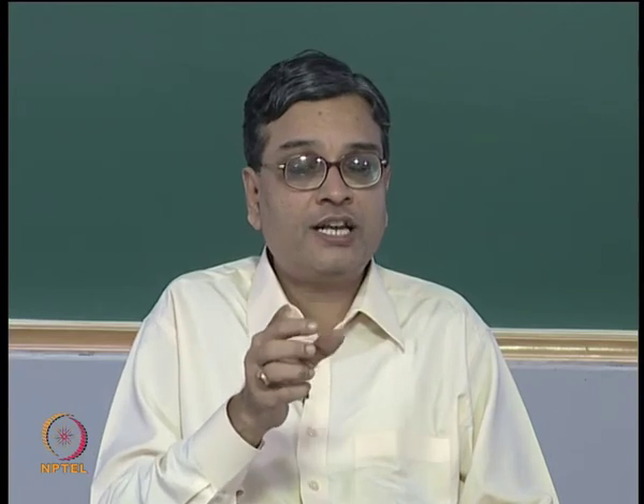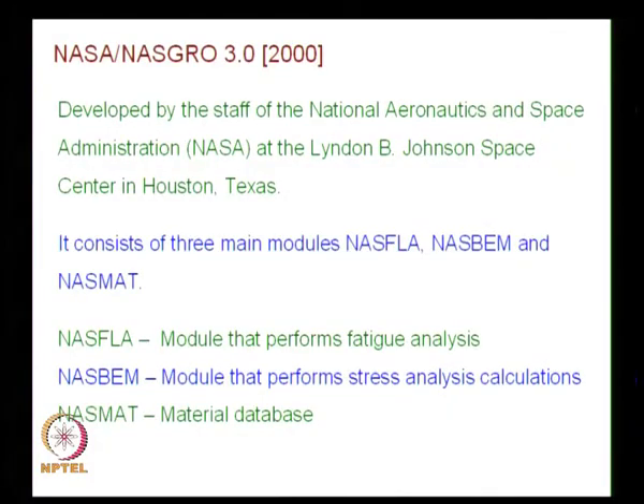I had also mentioned, when you have C delta K power m, we use it in Paris' law. We also use a similar form in Forman law. I had cautioned that the same C value you should not use. You should go to the material database, and then for that material, if Forman law is used, from that you use C and m. So, one of the successes of any of this fatigue growth calculation depends on what broader material database you have. So, the material database is very important, and thus specifies for what kind of materials you would be able to do crack growth calculations.